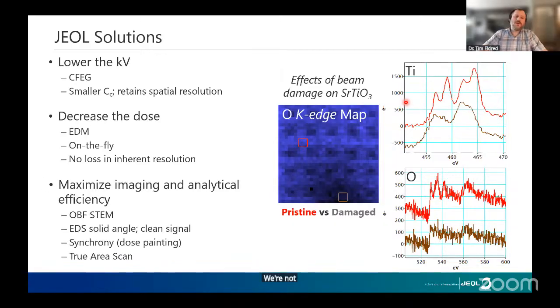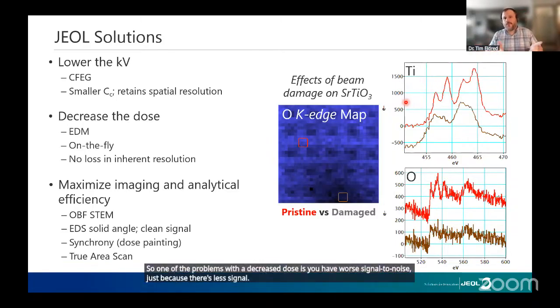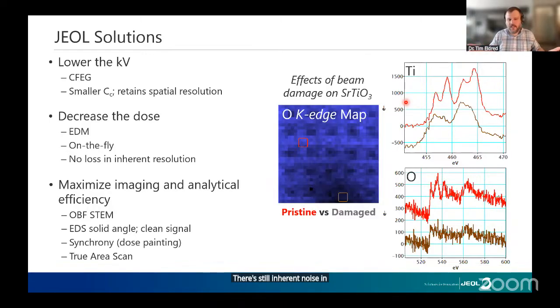We're not going to talk too much about analytically efficient techniques, but there are quite a few ways to, once you've decreased your dose, still get good signal. So one of the problems with a decreased dose is you have worse signal to noise just because there's less signal. There's still inherent noise in instrumentation. But by using techniques that have good dose efficiency, like OBF STEM and high solid angle EDS, you can still get the data you need at these lower doses.